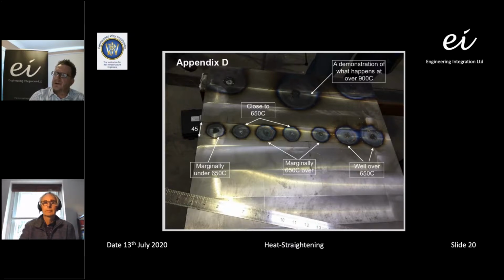Also, when we're actually heating, obviously the heat at the head of the torch is about 3000 degrees C, and you can appreciate that there's a lot of dispersal of heat occurring as you're applying the heat into the structure. So therefore, if you were using a thermometer or a temper stick to define it in practice, as soon as you take the torch away, the temperature probably drops instantaneously about 200 degrees C. So you're probably getting false readings. And if you're using temper sticks, you may actually overheat the structure inadvertently by the fact that a lot of heat has been lost out of the steelwork as soon as you move the torch away from it. So our preference is to utilize heating patterns to define the heat.